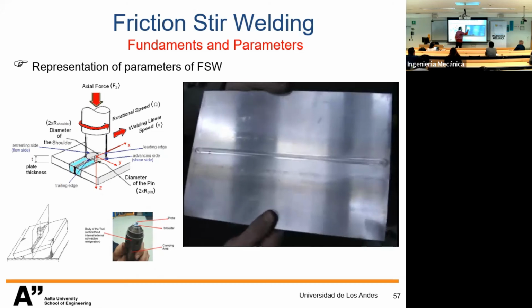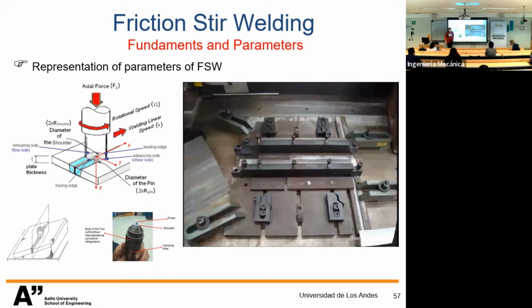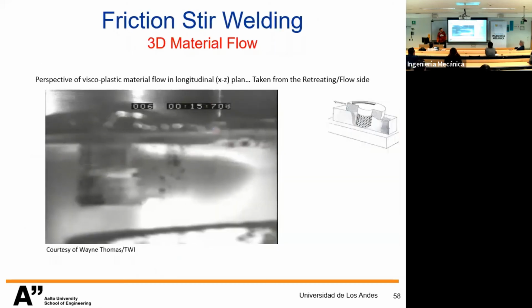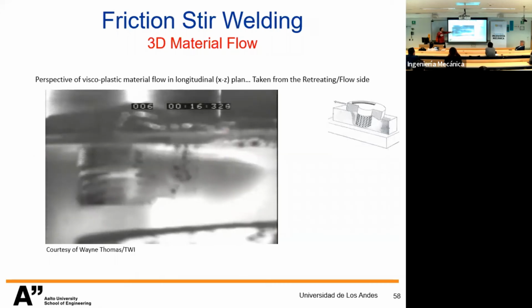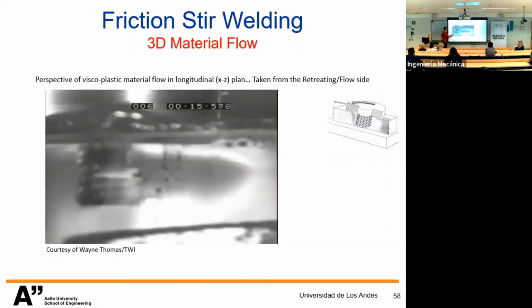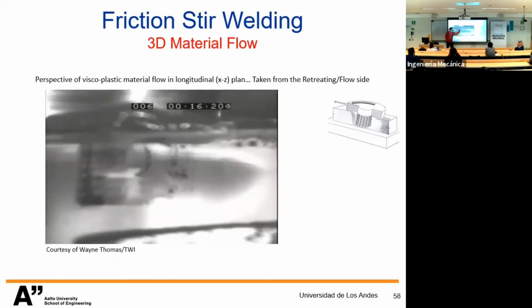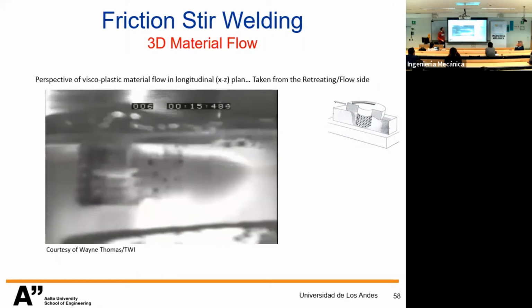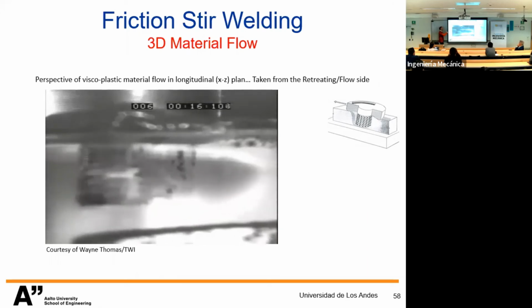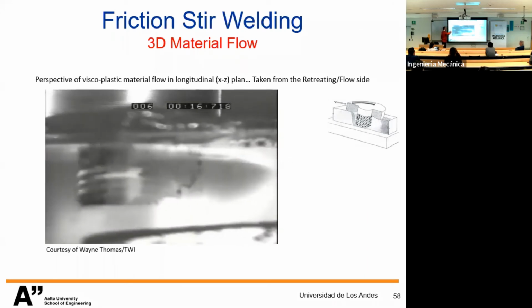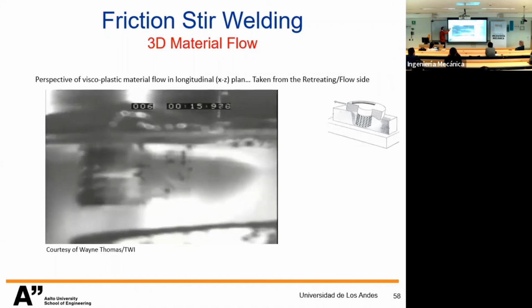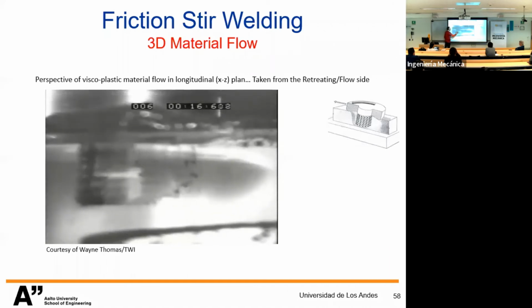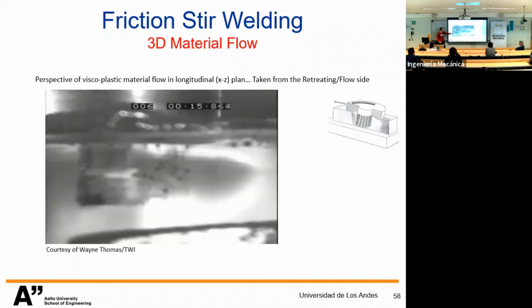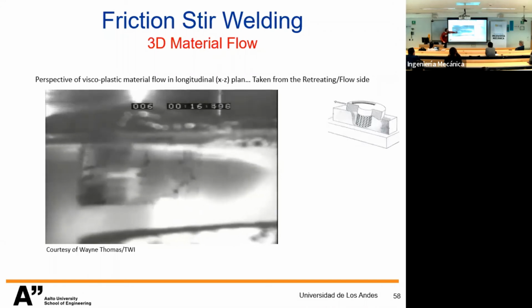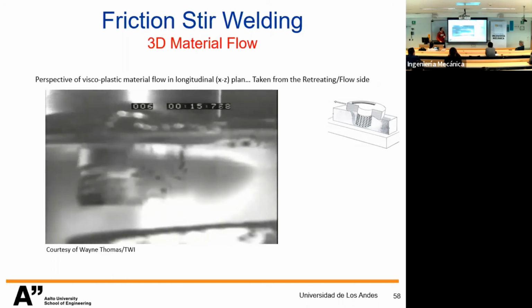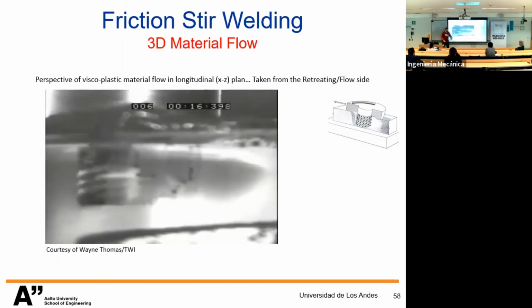So this joint has exactly the same origin as the base material strength effect. You can see here it applied in a polymer with some tracers to understand the three-dimensional flow of the material as it gets away from processing. So the material flow provides the heat generation and the plastic flow, and therefore the stirring effect and the quality of the mixture depends a lot on the features of the tool. So the geometry and features that we provide to the shoulder and probe provide the properties for the processed zone.